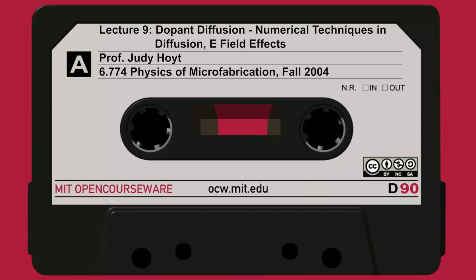Okay, so let's go on to slide 15, where at the top I've just reproduced that picture, a smaller version of it, just reminding ourselves of the relationship between Ci and Ni. Now, as we're looking at this lattice, we know that the atoms are relatively fixed in the lattice, but they do vibrate about their average position in a plane, and they're vibrating at some frequency, V sub d, which is called the Debye frequency. That number is typically on the order of about 10 to the 13th per second. So it's a pretty high frequency. They're vibrating about their average lattice positions at a finite temperature.